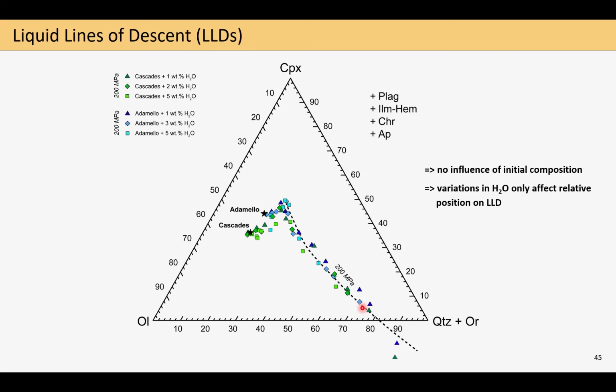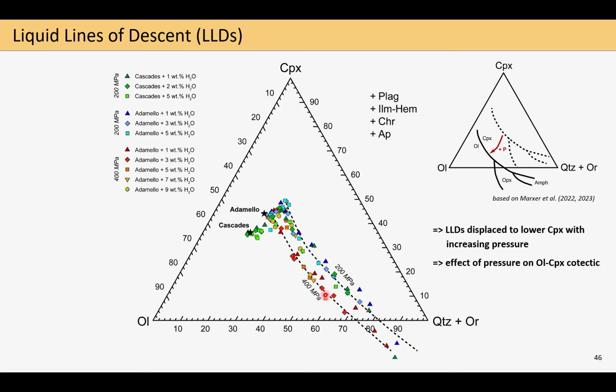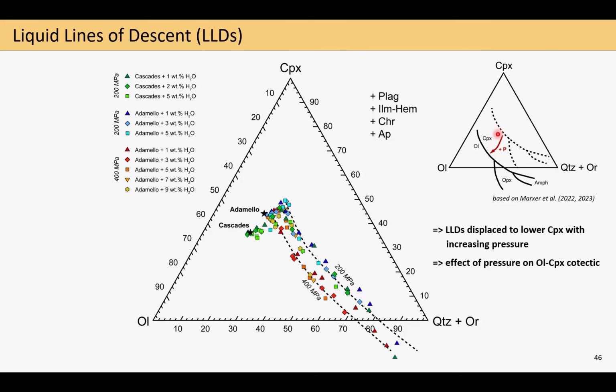And when we add now in these reddish and yellowish colors the 400 megapascal data for the Adamello, we see a shift of the liquid line of descent towards lower CPX components, thereby nicely illustrating the well-known by now effect of pressure on the olivine-CPX cotectic, which, as shown here in this schematic diagram, where an increase in pressure brings down this reaction or this cotectic curve towards lower CPX components. So this is now all very, very nice.